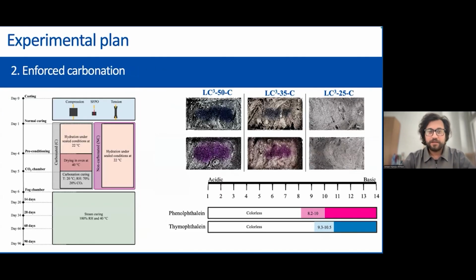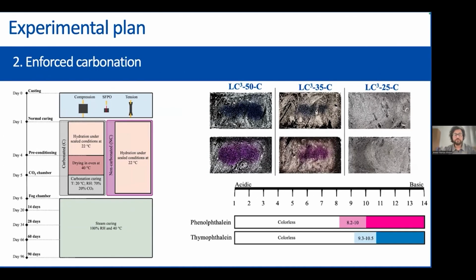The second pathway we explored was enforced carbonation. The idea was to lower the matrix alkalinity after early hydration so PET fibers would survive longer. And a useful side effect of introducing enforced CO2 in the matrix is that it doesn't just stay in the system as gas. It actually interacts with the cement phases, forming calcium carbonate as a stable phase. So that means chemically bounding. We are trying to chemically bound the CO2 inside the matrix. Hence, in this way, we can sequester CO2 while bringing the pH down.